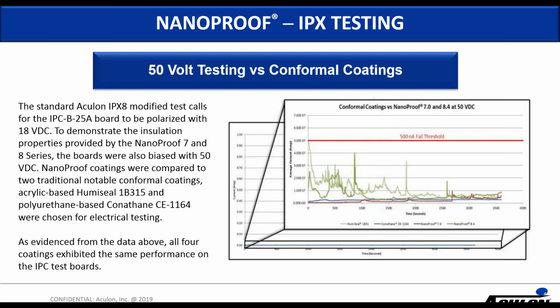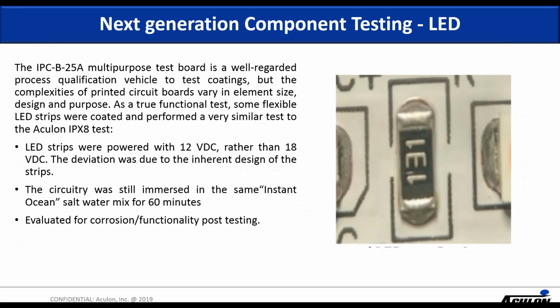But these two conformal coatings, the acrylic and the polyurethane, which we know from experience on customer parts don't pass immersion testing, both appeared to pass this test as well. So they're both below the 500 nanoamp threshold. There's some spiking up to 300-400 nanoamps, but they still are considered a pass. So that tells us that, we know from practice that the traditional conformal coatings aren't getting to IPX7 or IPX8 levels of immersion performance.